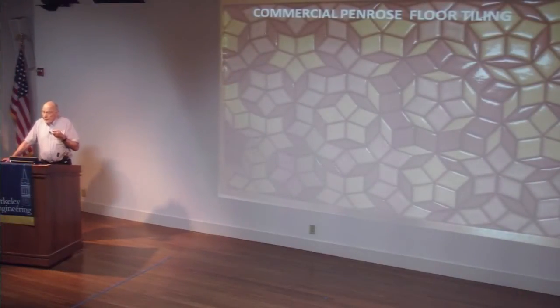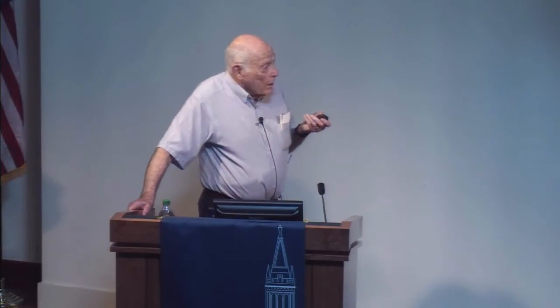And I often say that it's awful to have periodicity. I mean, I know it exists most of the time and it's real, but just think of it: if a tetrahedron is the best way of packing atoms together, in order to make either HCP or FCC, for every tetrahedron you have to add an octahedron. And that's not a good thing to do, but you want to pay that penalty in order to have periodicity. You can make an icosahedron, which is 20 slightly distorted tetrahedra, but then you have to worry about packing them because it has a fivefold axis.